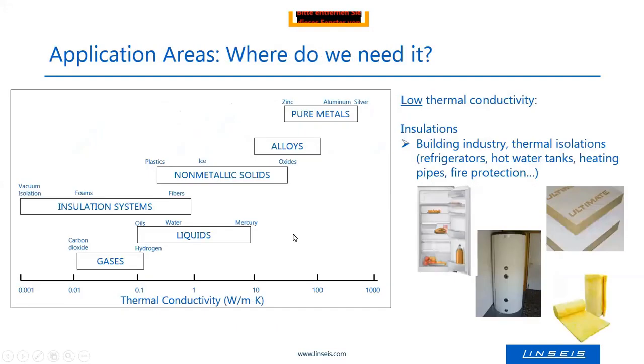The application areas can be very different. So for some applications, you need low thermal conductivities. For example, for building materials to isolate the buildings, for refrigerators or boilers, you need insulating material, and the goal must be or should be to reduce the thermal conductivity. And for these samples, you measure in the range of 0.001 watt per meter Kelvin up to 1.